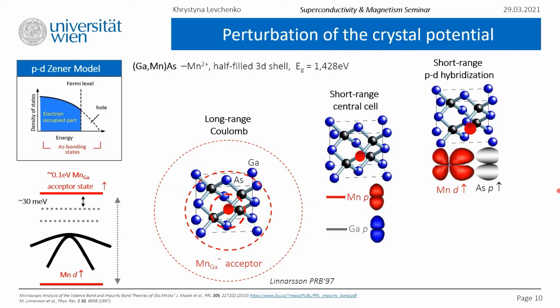What will happen if we start increasing the concentration? When we are still at a low concentration of manganese, below around 0.5%, the distance between the holes bound to the manganese ions is much larger than the size of the bound hole, which leads to an insulating phase. With a medium concentration between 0.5 and 1%, we already see overlapping to form an impurity band and an insulator-metal phase. With a high concentration, 1% and more, we see ferromagnetism at low temperatures.